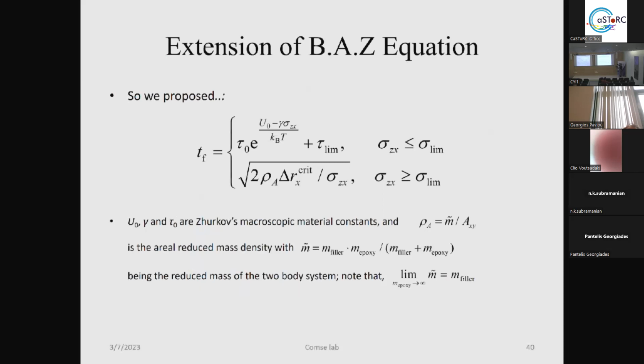So what we proposed is that depending on the stress, if you have stresses smaller than the sigma lim, you have an exponential behavior of the time of failure, adding, of course, the numerical difference, the tau_lim term that we have in contrast with the Zhurkov. And in the second regime, we have a linear response, which depicts the acceleration motion, and which says that as far as you put high stress, it has an acceleration motion because of the totally destroyed interface.